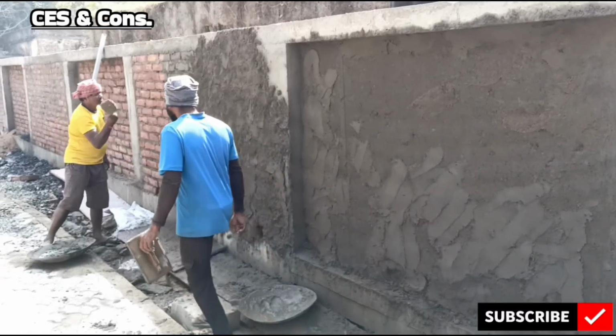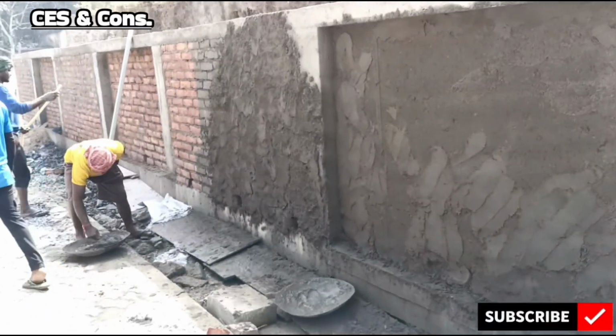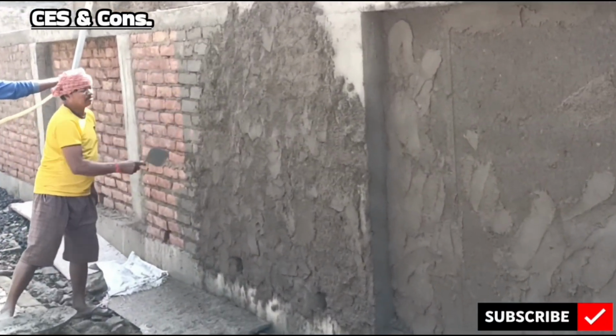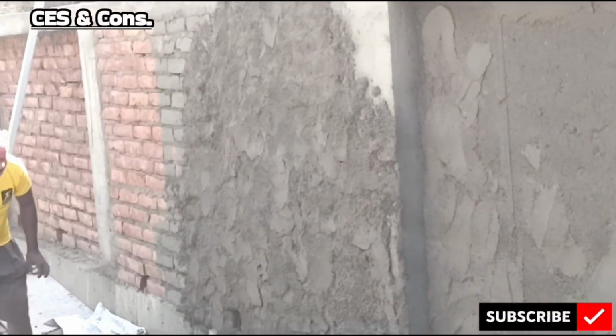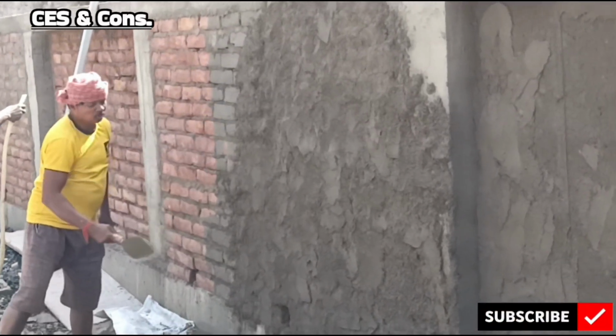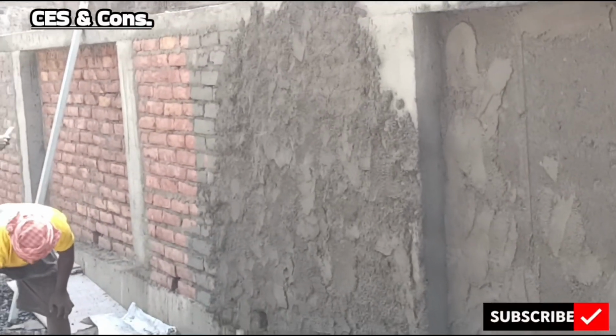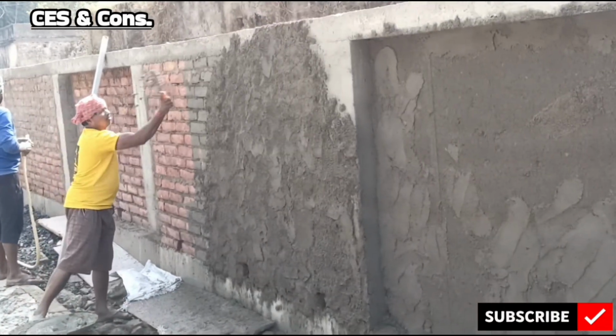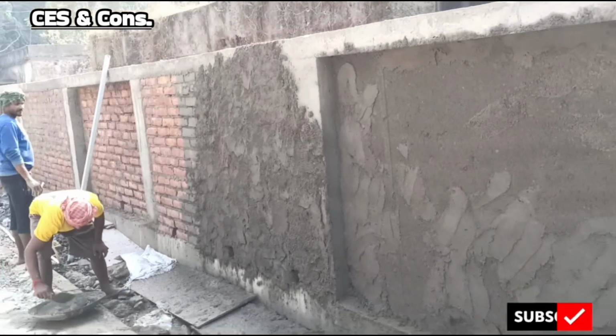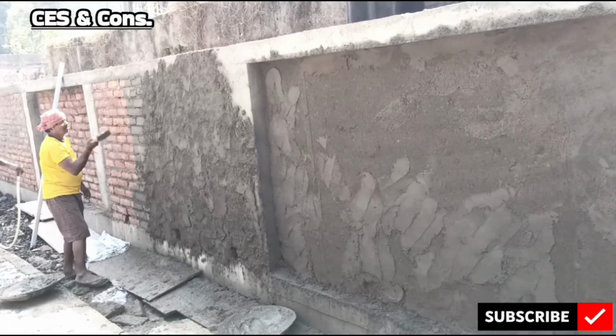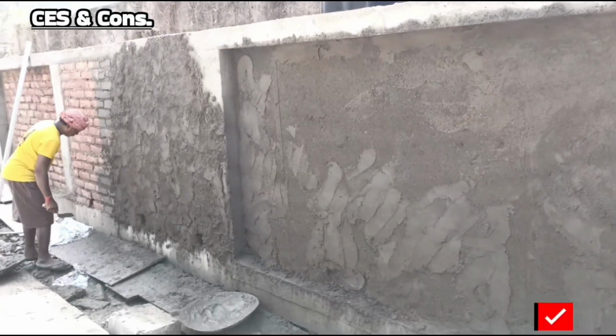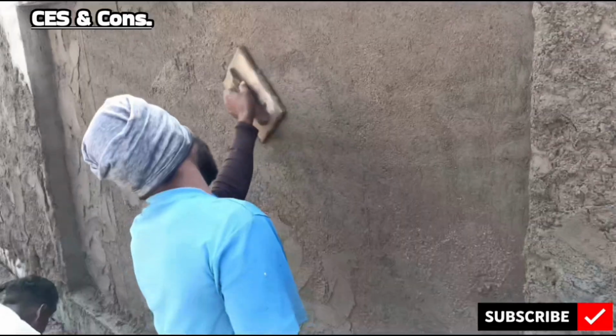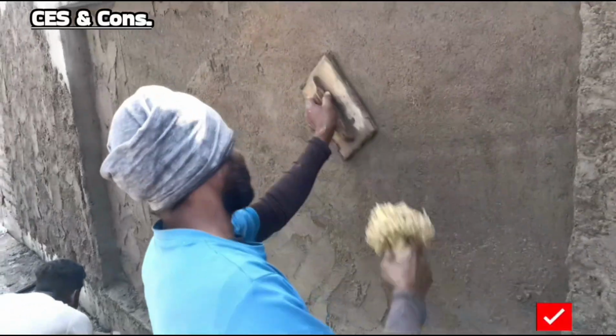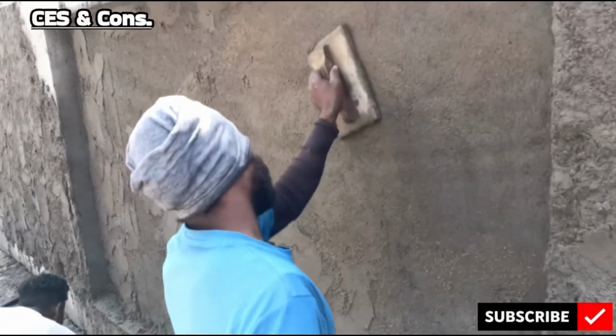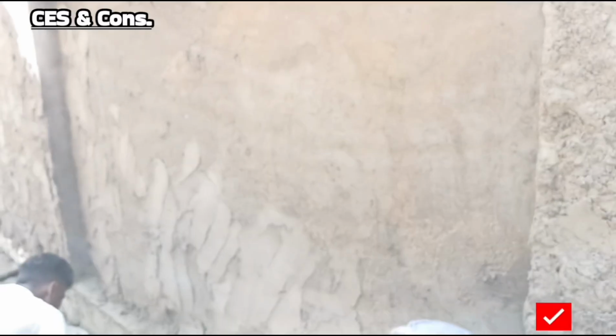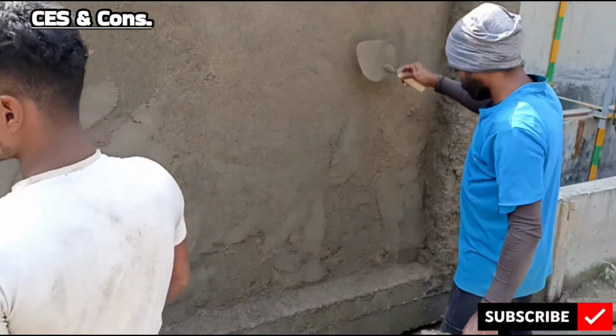Thickness of plaster. For internal walls, plaster thickness is usually 12 mm to 15 mm. For external walls, it ranges from 15 mm to 20 mm for better weather protection. In special cases, 2 coats of plaster may be applied: the base coat 10 to 12 mm thick for leveling and the finishing coat 3 to 8 mm for smoothness and neat finish. Preparation of background surface.